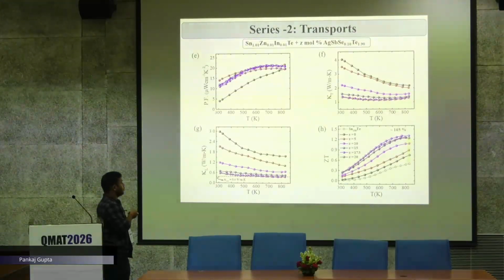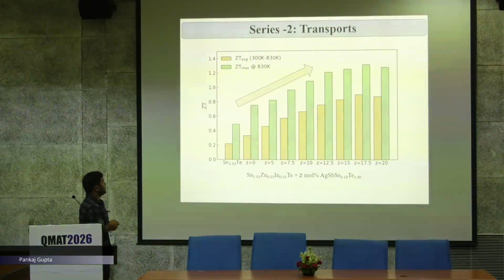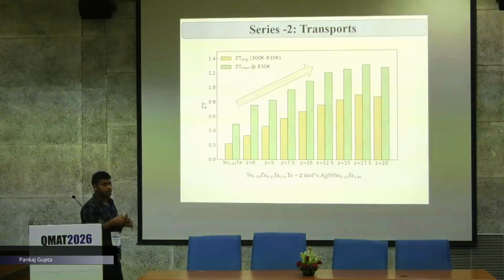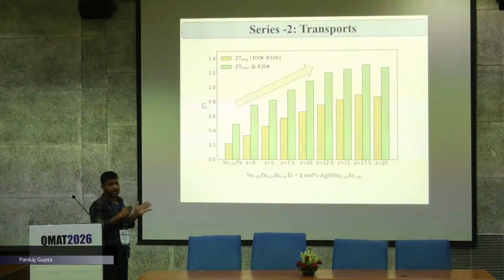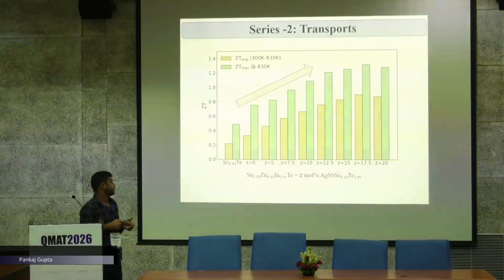That is the excellent point of this work, and by incorporating all these effects we could get around 165% enhancement in the overall zT. Here you can see I have done a systematic study of all the samples, and we could increase zT and average zT. Average zT is more important because this is the zT which impacts the thermoelectric device efficiency, and we could get a huge enhancement of around 300% in the average zT and 165% in the highest zT. This is a summary.